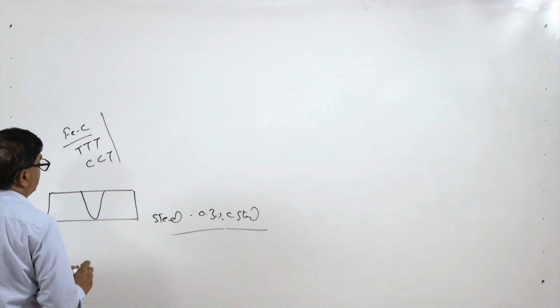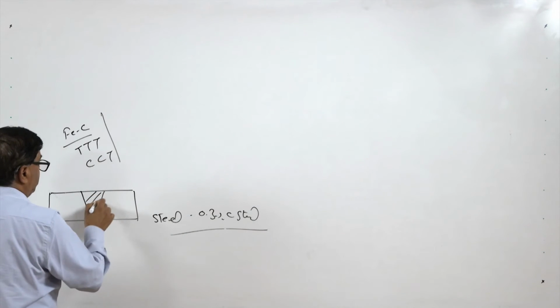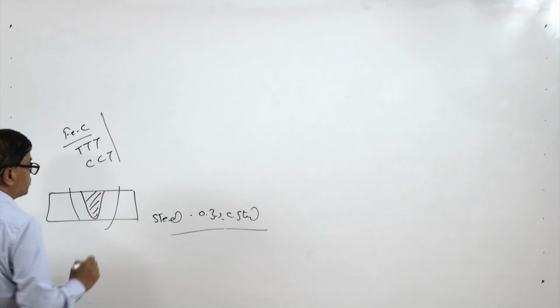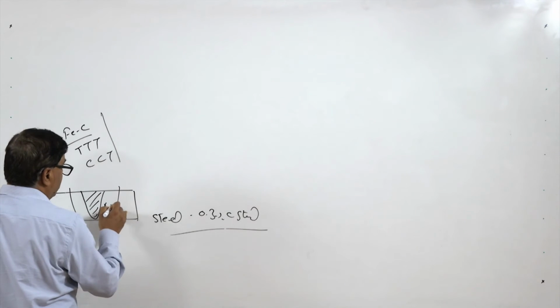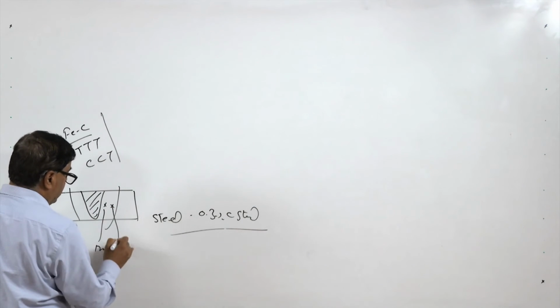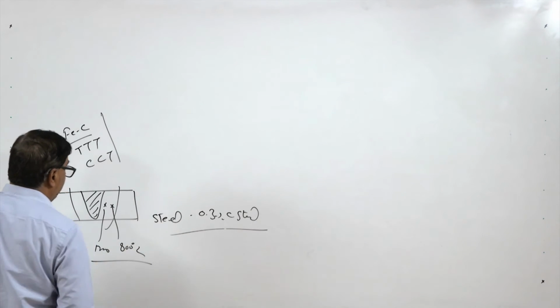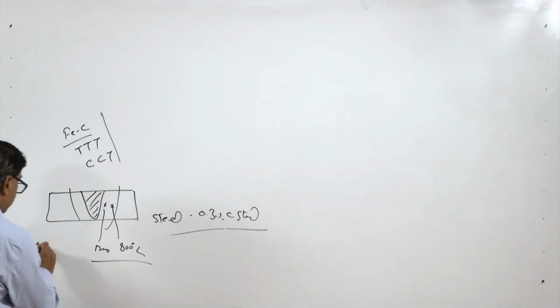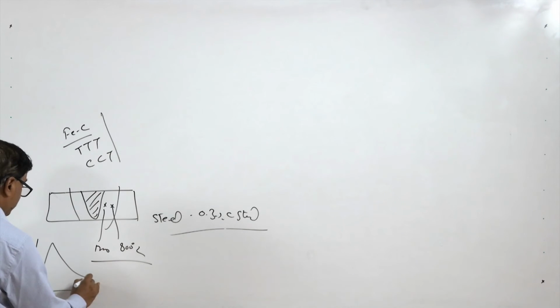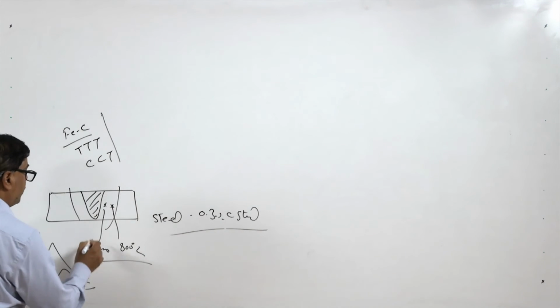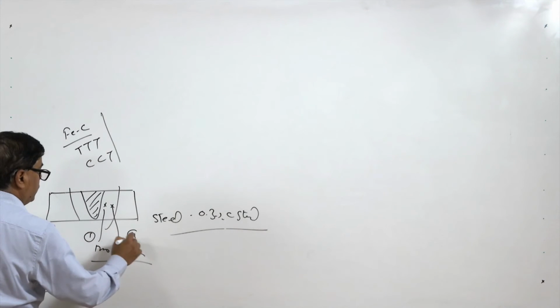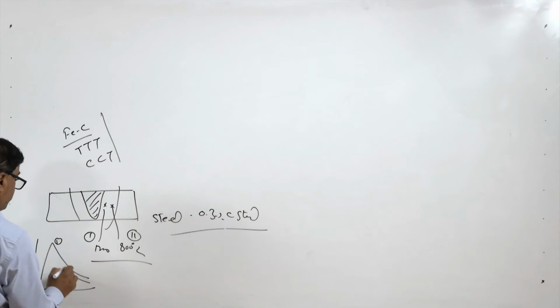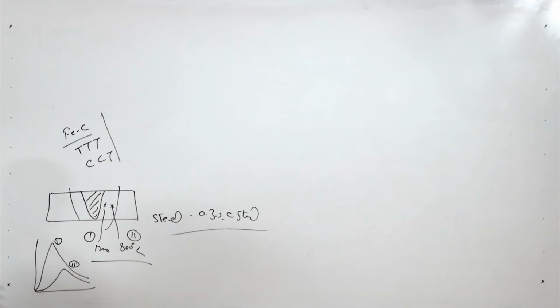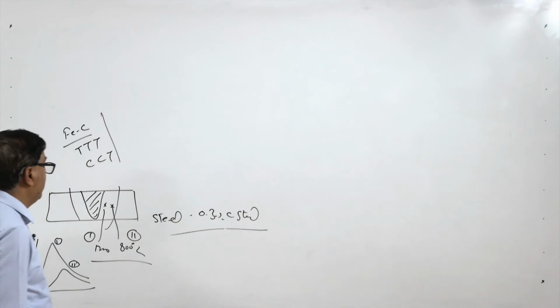So, when the steel is welded, this portion will reach the molten state and the areas close to the weld will reach different temperatures like 1200 degree centigrade, 800 degree centigrade, etc. And we know that different points will experience different weld thermal cycles like this. For point 1 and point 2, the weld thermal cycles are like this. Point 1 will experience the greater temperature for longer duration as compared to point 2. Point 2 will experience lower temperature as compared to point 1.